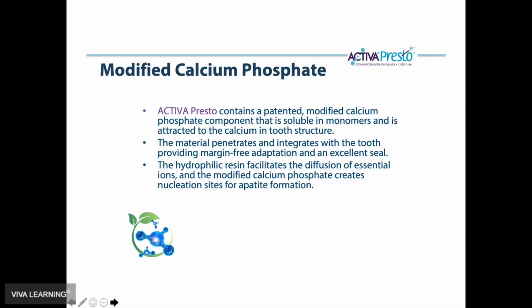The thing that's unique about Activa Presto is that it has a modified calcium phosphate. This contains a patented modified calcium phosphate that's soluble in monomers and is attracted to the calcium in tooth structure. The material penetrates and integrates with the tooth, providing a margin-free adaptation and an excellent seal. This hydrophilic resin facilitates the diffusion of essential ions, and the modified calcium phosphate creates nucleation sites for apatite formation. In other words, helping to seal margins and maintain margin integrity.